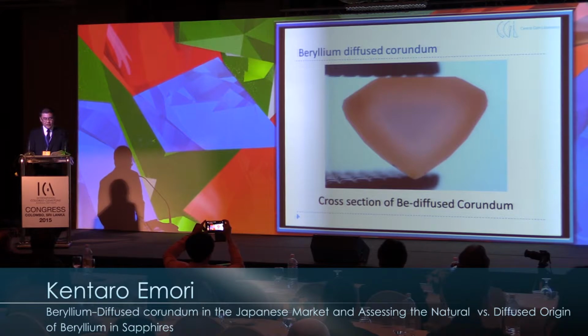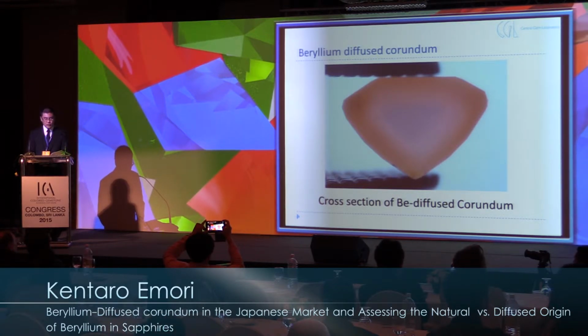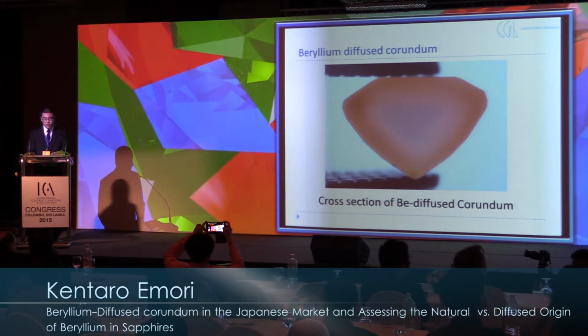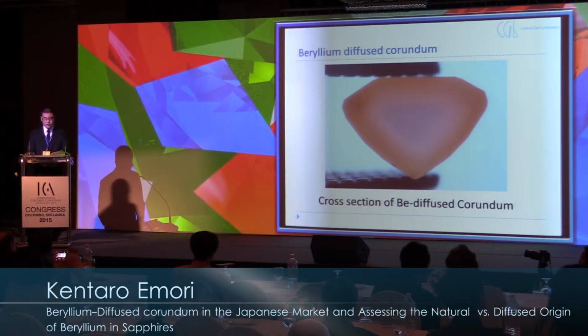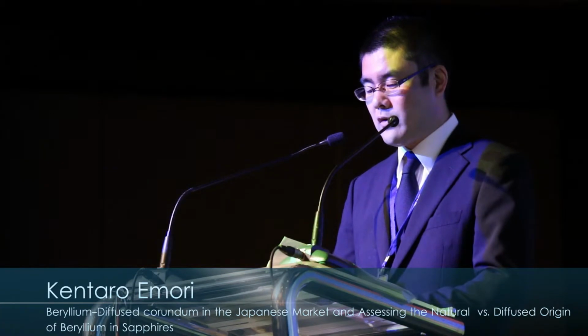Beryllium-diffused treatment is usually done after preforming, and most stones show an observable surface conformal layer. If a surface conformal layer can be observed, this stone has had elements diffused from outer sources. However, in some stones, beryllium has diffused in the whole region and colored uniformly into the inside. Such stones do not give the color zoning shown in this photo.